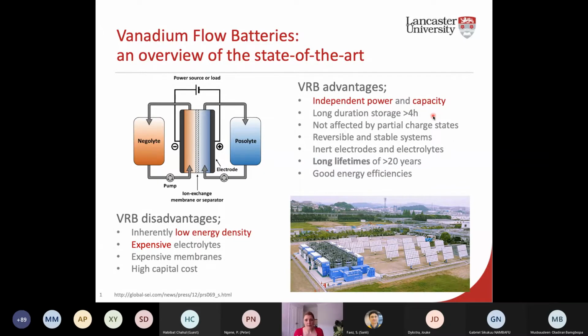The species are typically reversible and stable in their charge states, which is really critical. And because all the processes are happening in the solution phase, you're charging the solution phase species and it's nothing to do with the electrode as such. The electrode, like I said, is just an agent in the process. That means that you have inert electrodes, and the solvent itself is just sulfuric acid. So you're not losing efficiency or capacity or changing the properties of the solution, and that means you end up with a really extended lifetime.